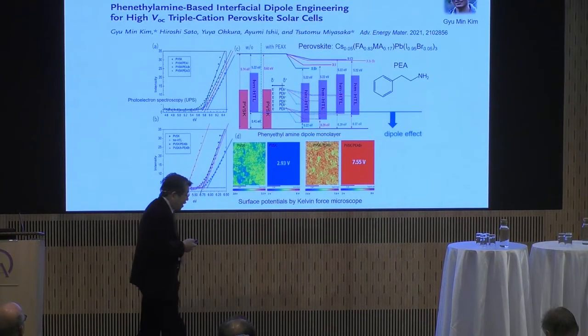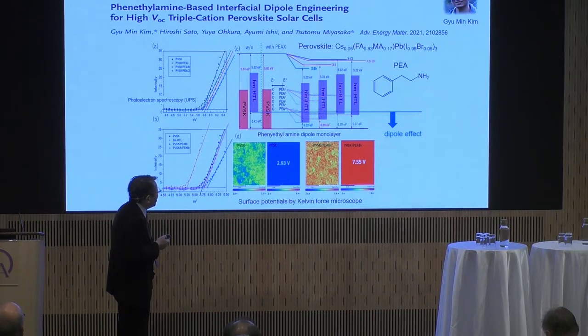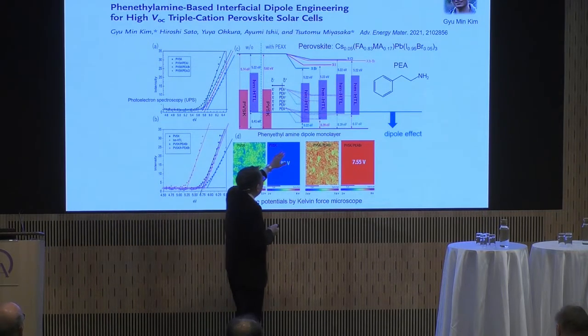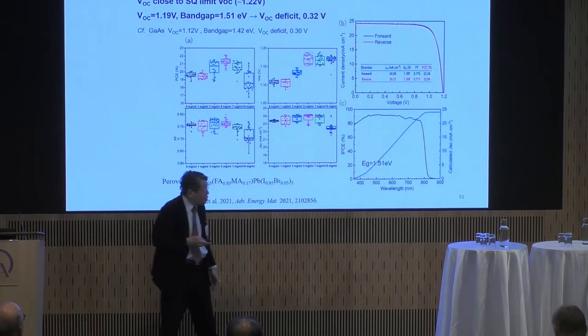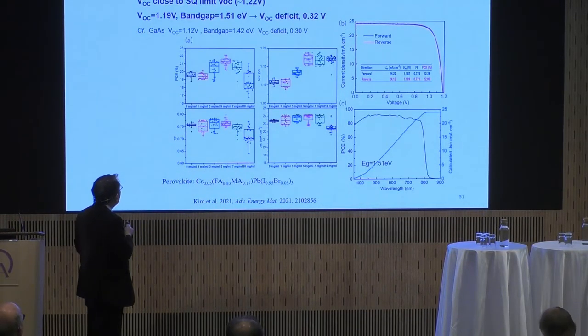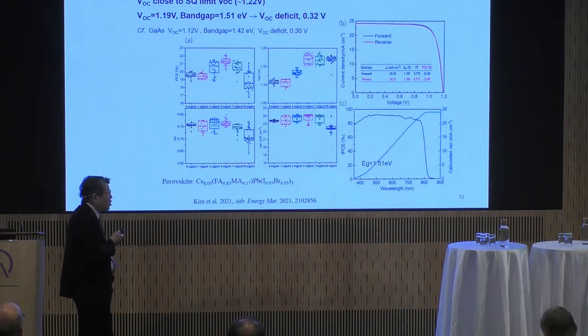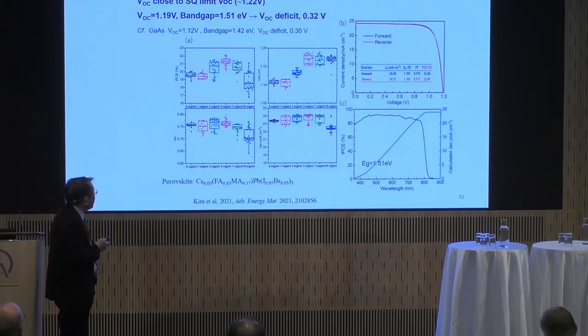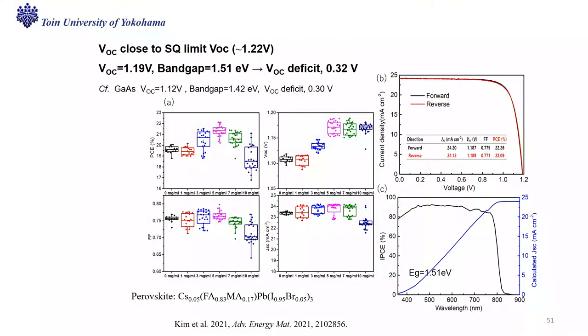Interesting, very interesting. And this is some typical material, phenylethylamine. We coat the interface of perovskite with this one to generate the dipole, this is a field at the interface, to shift the whole transport material's work function. The result is we could get relatively high voltage, 1.19, but the gap is relatively low, 1.51. That indicates voltage loss deficit is limited to 300 millivolts. It's very, very low. So this kind of close to theoretical limit of photovoltage, we could get efficiency over 22%.